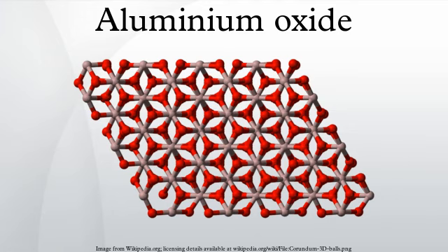The product aluminium oxide tends to be multiphase, that is, consisting of several phases of aluminium oxide rather than solely corundum. The production process can therefore be optimized to produce a tailored product. The type of phases present affects, for example, the solubility and pore structure of the aluminium oxide product which, in turn, affects the cost of aluminium production and pollution control.